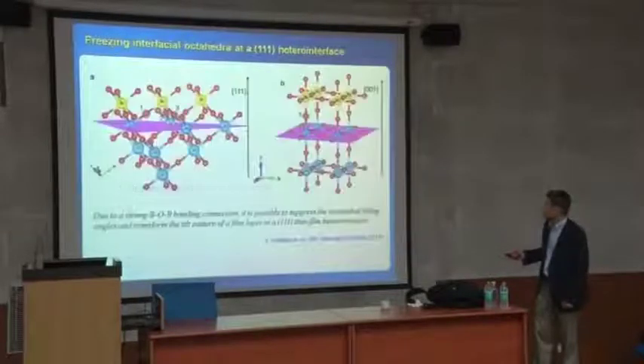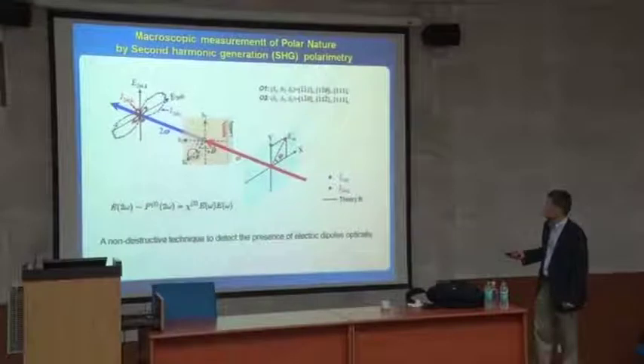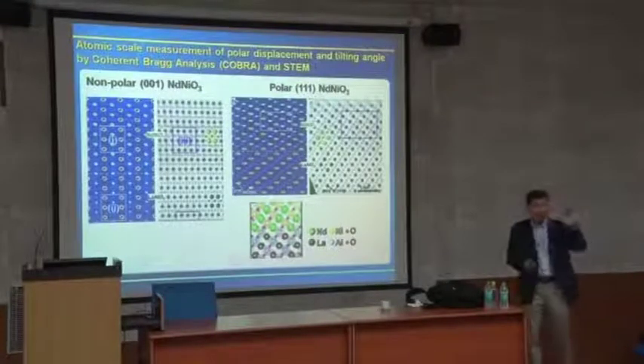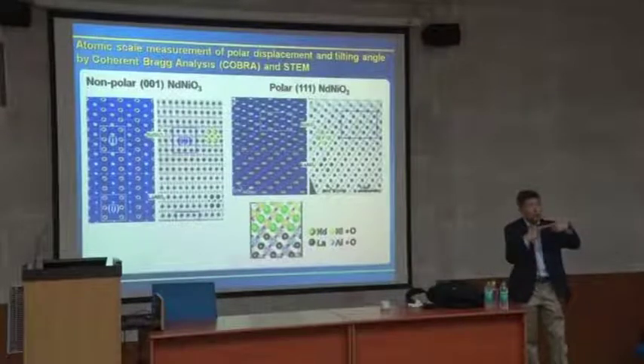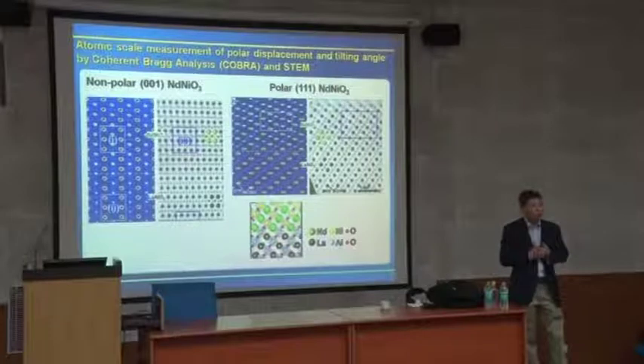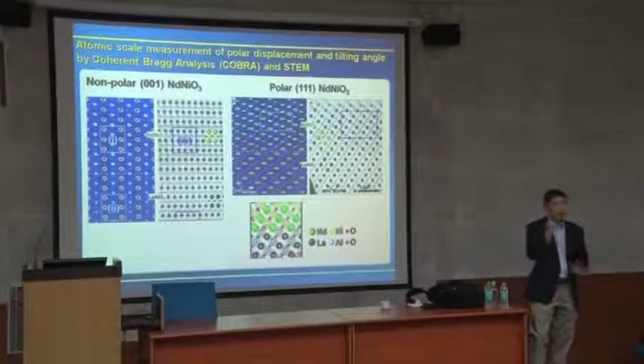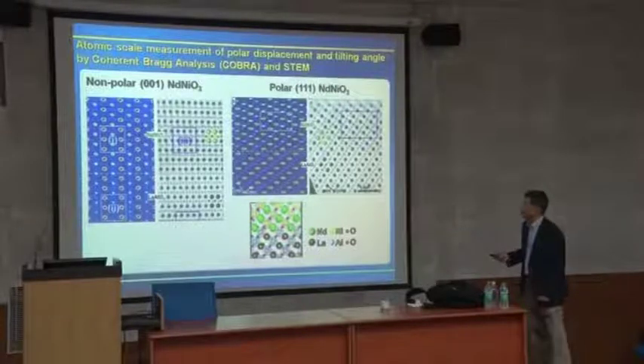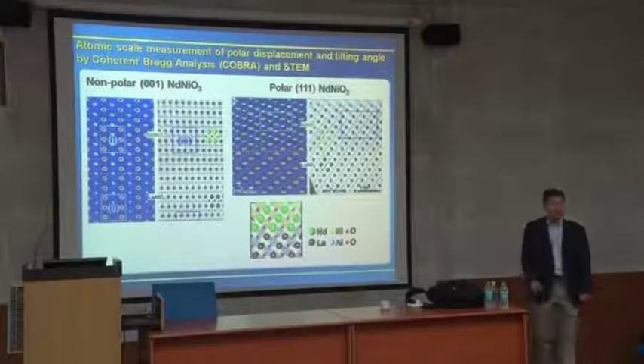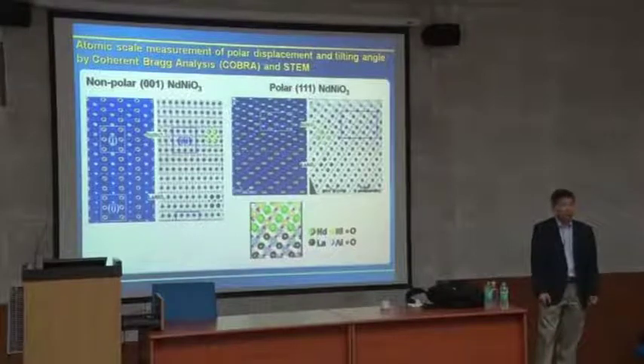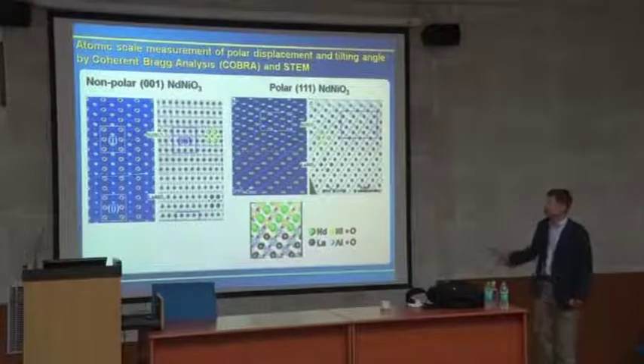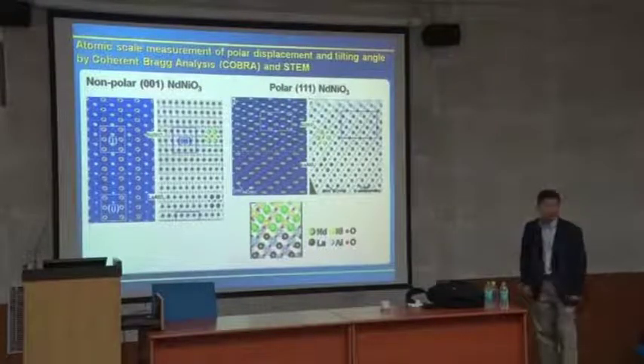So what you did here, your atomic positions and also the tilting angle, you measure both. How do you measure those things? Which technique can really tell extremely small changes in atomic distance within the unit cell, and very tiny changes of tilting angle? The method is a combination of two different methods. One is scanning transmission electron microscopy, we call STEM, and that shows the actual position of all the atoms, including oxygen.